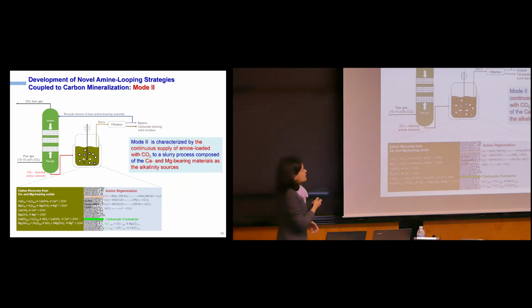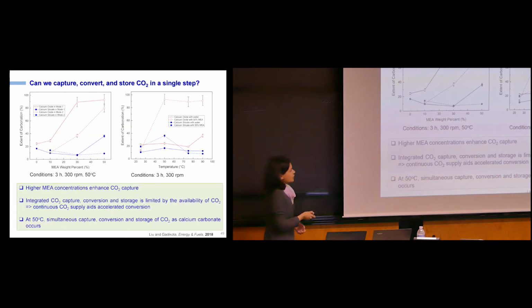The second step is if you already have a CO2 capturing facility where you have an absorber in place where CO2 is being captured, can we just stick in another reactor where we can chemically regenerate the amine and we can produce high purity calcium magnesium carbonates? So this is what we call mode 2. Now let's look at what that gives us.